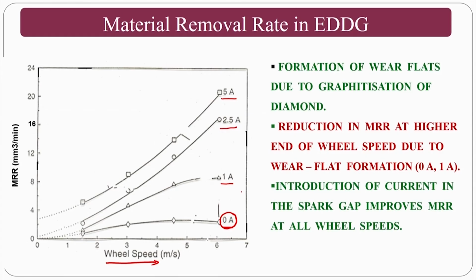As you see, for 1 ampere, you are giving a very small amount of current. So the reduction of MRR at the higher end of the wheel speed is due to wear and flat formation, that is nothing but the glazing appearing. At the same time, introduction of current in the spark gap improves the MRR in all cases. As you increase the current, your sparking will improve, and at the same time your melting and evaporation will improve, and most of the material you can remove by two actions: melting and evaporation as well as your abrasion action. Okay. In all conditions abrasion is constant, however melting and evaporation will vary and will increase in this direction. So your material removal rate obviously increases.